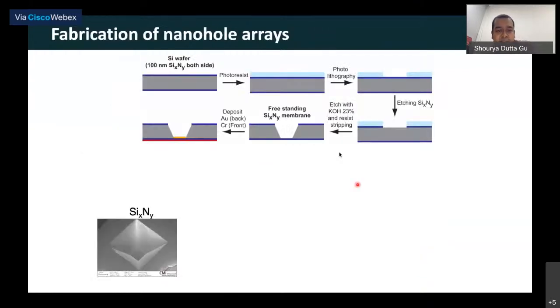So the way we make these structures, we have a multi-step lithography process. So we start with a silicon wafer coated with silicon nitride on both sides. We coat the top part with the photoresist and then we do a step of photolithography to make the apertures that we want. Then we do the etching of silicon nitride and then do the etching of silicon using KOH. Now, KOH etching of silicon 100 leads to the formation of basically what you call a pyramid kind of shape that is shown here. So this is the actual fabricated structure that we have.